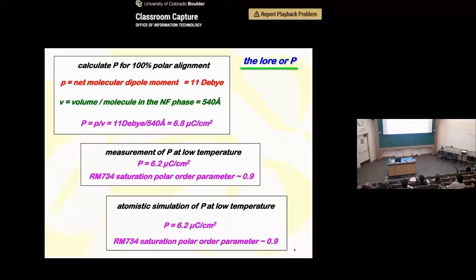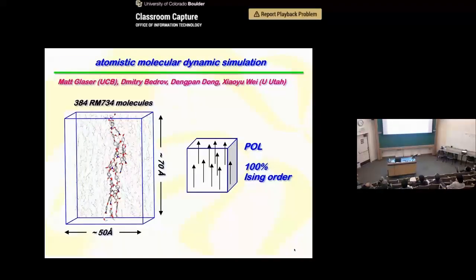Then we wanted to understand this better, so we turned to atomistic simulation. This is a simulation box with 384 of these molecules, with periodic boundary conditions. The simulation is started with all the dipoles in the same orientation, all the molecules in the same orientation. And during the simulation, they don't flip over. So we have 100% Ising order. There's a big barrier for end-to-end flips. So that's rare enough that, with the resources we have for the simulation, we never see the flipping.